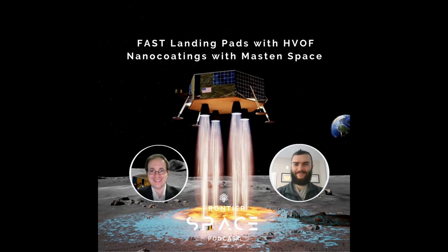I wonder if there's a way we could help quantify just how much dust you guys could help pave and mitigate in terms of quantifying the ejecta plumes. The current design requires about 300 kilograms of mass delivered to the lunar surface. That's with the engines and the alumina and everything as a bolt-on package, so it can be used on any number of lunar landers, and it would create about a 6-meter diameter landing pad. That would be a dust-free zone around the lander.